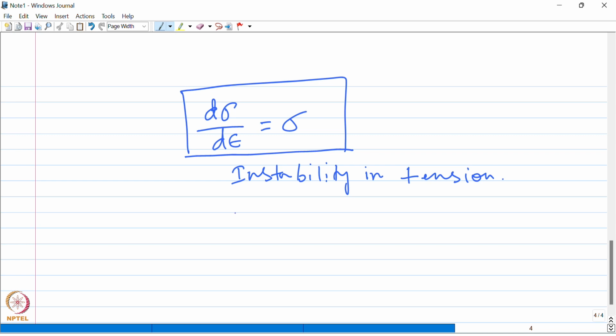Alright. We can also obtain the true strain at which this occurs if we consider this equation between true stress sigma and true strain epsilon. They are related by this equation, and from here we know that the strain hardening exponent n is nothing but the slope of the plot between log sigma and log epsilon. That is, n is equal to d log sigma by d log epsilon.